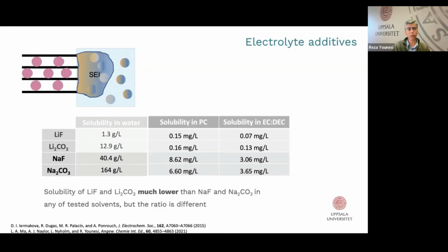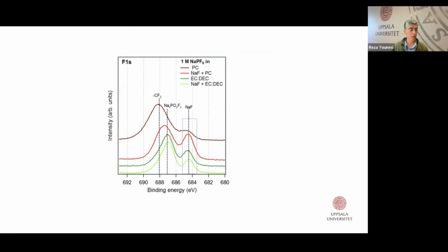So by adding sodium fluoride and sodium carbonate to the system, we did the same type of experiment to measure the solubility and aging, but we also did synchrotron XPS measurements to see how the composition of SEI has changed. If you look at the green spectra at the bottom, those are in EC:DEC-based solvents with NaPF6.